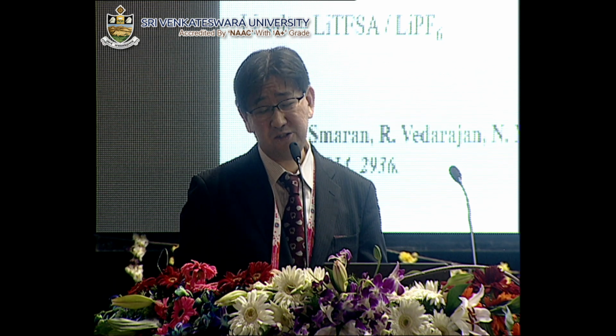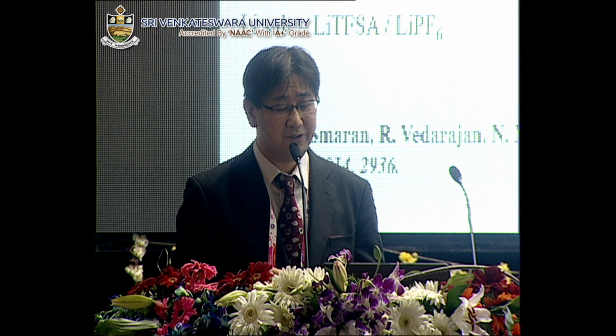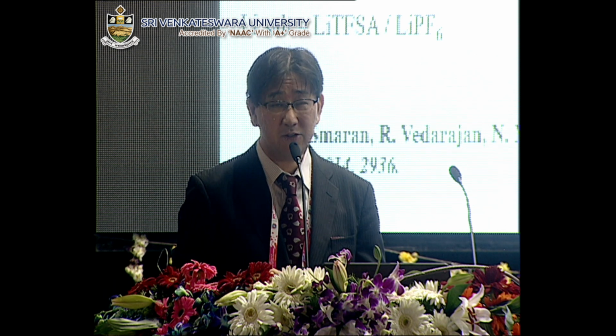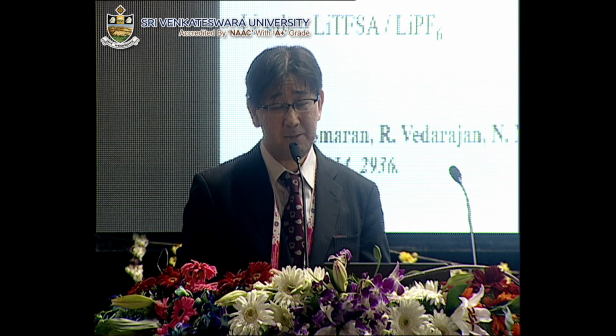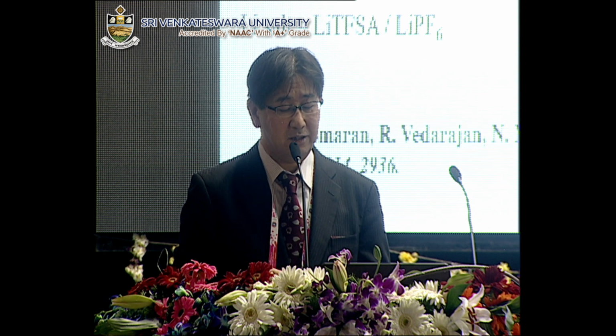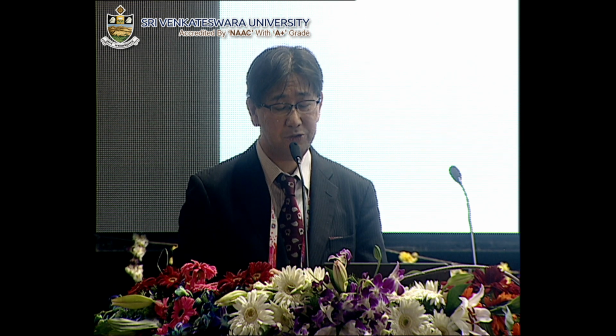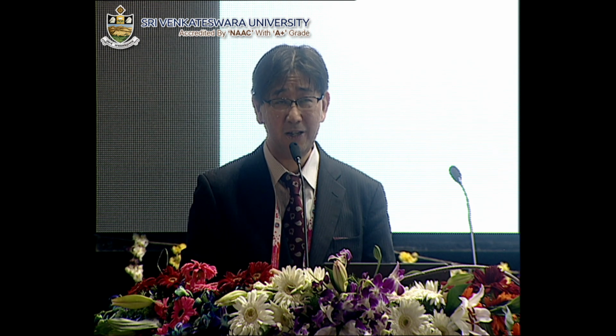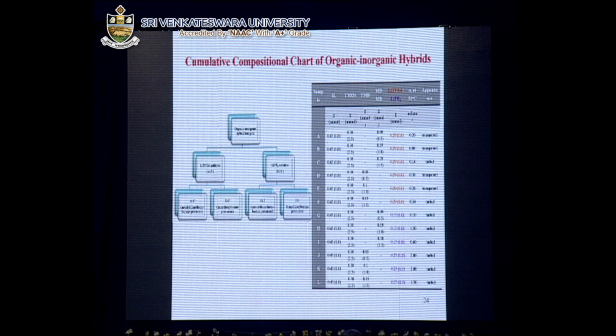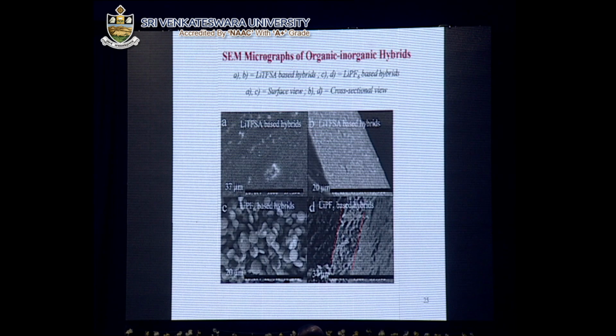And sol-gel condensation was carried out for tetramethoxysilane and alkoxyborane in the presence of a catalytic amount of hydrogen chloride. And after 1 week of reaction at 60 degrees Celsius, the condensation was almost completed, and successfully the desired material was obtained in a wide range of material compositions. Particularly when the additive was lithium TFSA, generally transparent materials were obtained. On the other hand, when lithium PF6 was added, generally only opaque materials were obtained.